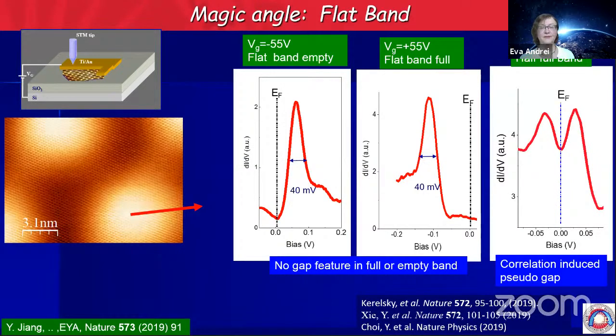And sure enough, when we bring the Fermi energy within this flat band, we open a gap. Actually, this is a pseudo gap. The gap doesn't go to zero. The density of states doesn't go to zero at the Fermi energy. So we see that we have induced a correlated state. We have induced that gap, and we can now look at what's the nature of this gap.